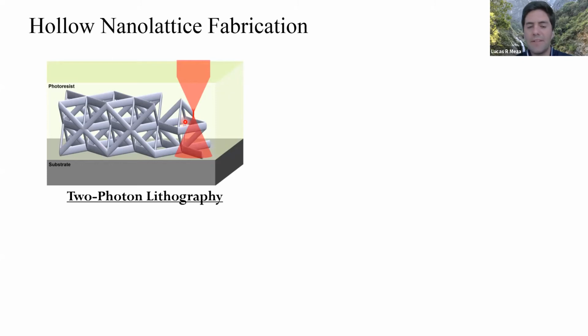So effectively what we have is a nano 3D printer. You shine infrared light into your material. Infrared light alone isn't enough to cross-link the material. So anywhere the red light shines doesn't cross-link, it just stays a gel until you get to a very narrow focal point. And here, at this narrow focal point, you have a statistical likelihood of getting two infrared photons absorbed. So those two infrared photons have the same energy as one UV photon, which most of these photoresists are designed to cross-link using. And so you only get cross-linking at that focal point.